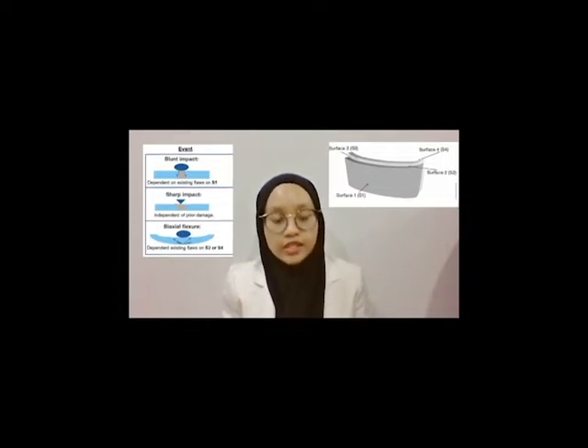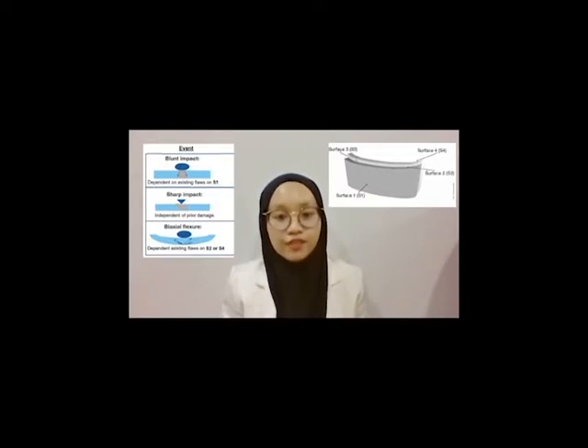Upon contact, the laminate flexes away from the impacted object, creating tensile stress on surface 2 and surface 4, which can activate existing defects on these surfaces and lead to radial or median fracture. And look at this figure. For blunt or Hertzian contact, since failure is based on pre-existing defects, parts were pre-abraded and Hertzian contact stress was applied to the windshield using a 1 gram stainless steel ball bearing at a 45-degree angle of incidence.